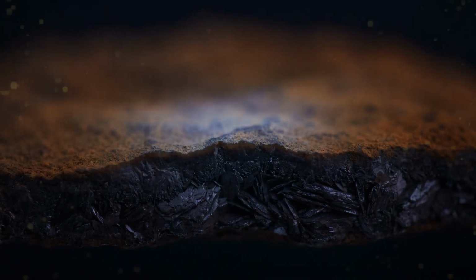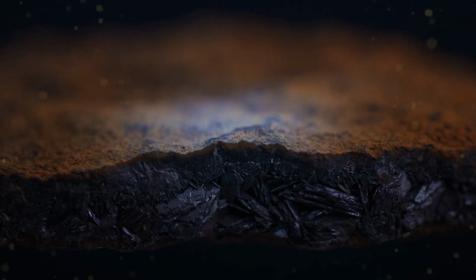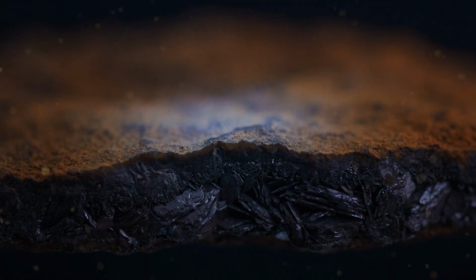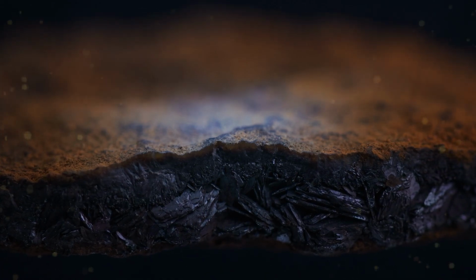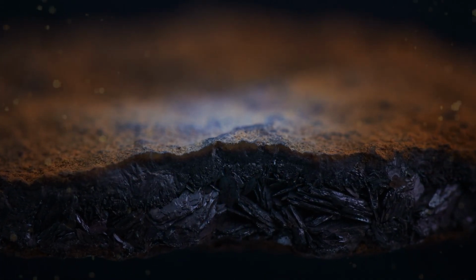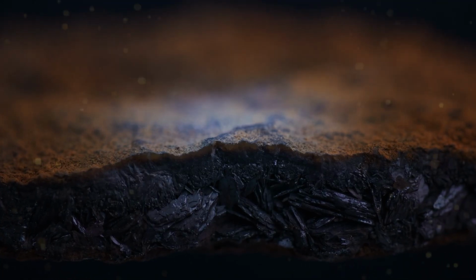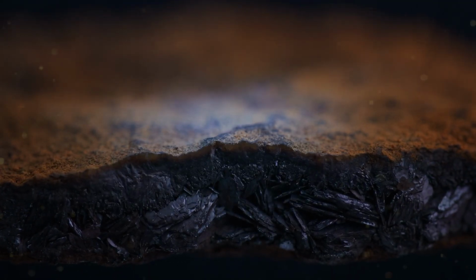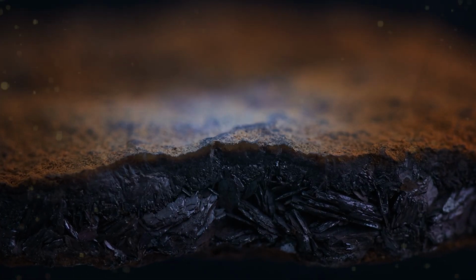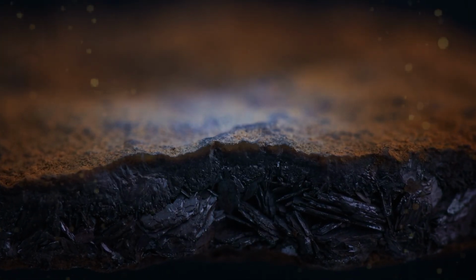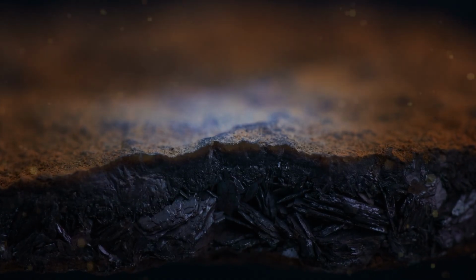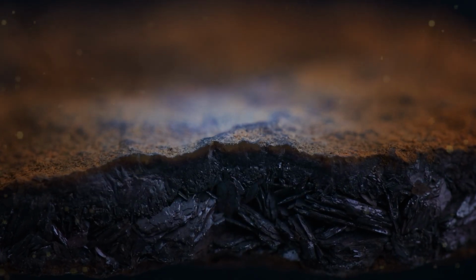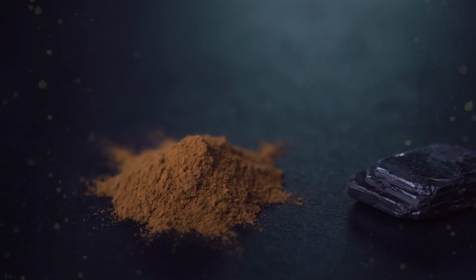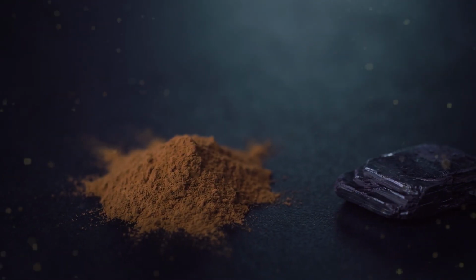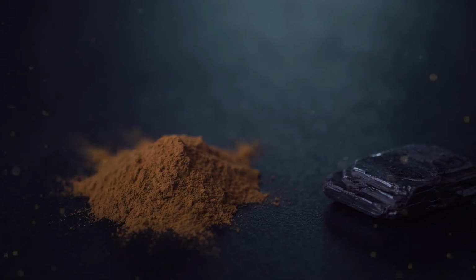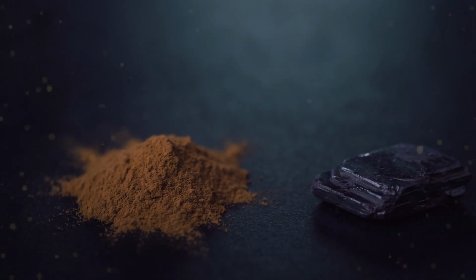The dust is carrying a chemical signature of cold, rapid, wet oxidation, and then effectively frozen in that intermediate form by conditions that changed before the transformation to a more stable phase could complete. What this means in practical terms is that the Martian dust tells a different chemical story than the hematite in the rock beneath it. The dust says cold, fast, wet, incomplete. The hematite says dry, slow, and fully committed.